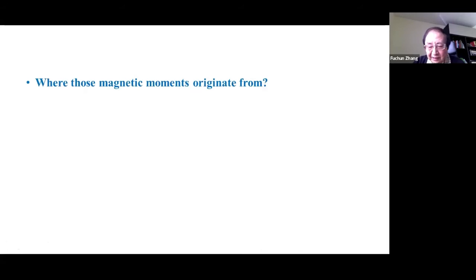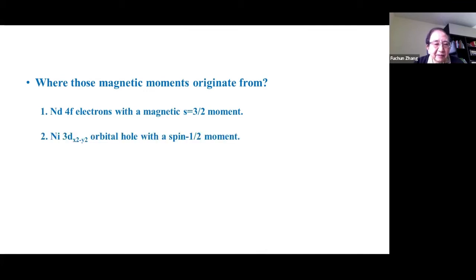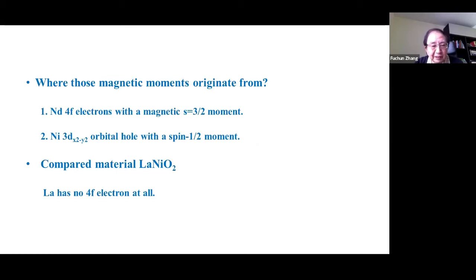So you may ask the question, where does the magnetic impurity come from in this compound? One possibility is the neodymium 4f electron, which has a magnetic moment 3/2, while the nickel moment is spin 1/2. However, lanthanum nickel O2 has a similar behavior, and lanthanum has no 4f electron. So the conjecture must be that it comes from nickel spin 1/2.